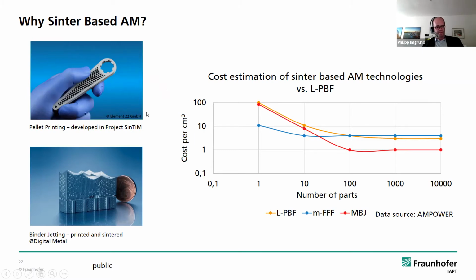We're using either a metal powder bound into a polymer matrix and processed by filament, like the standard 3D printing process that you may know from your home printer, or by the so-called binder jetting, where you don't use a laser for consolidation, but an inkjet head that prints the ink and consolidates the powder. I have a video on that in a couple of slides. And the main advantage of the pellet printing or filament-based printing is that you can use cheap machinery, and it's well usable for prototyping. So up to 10, 20 parts. It's way cheaper to use than laser powder bed or binder jetting.